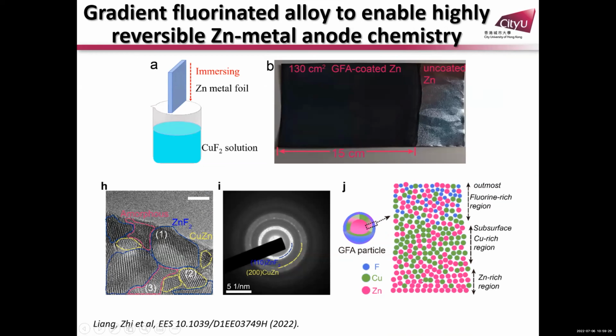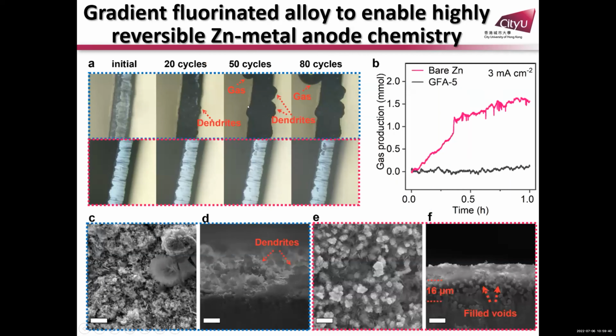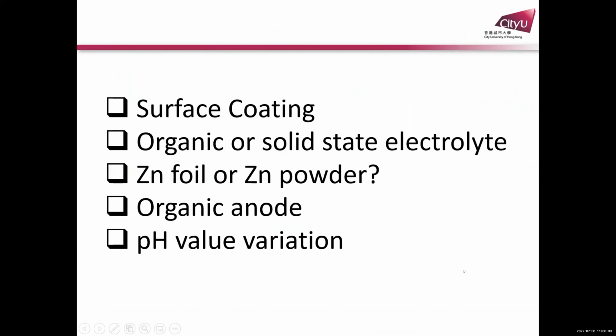So in this work, we develop a kind of gradient coating with zinc fluoride and alloy on the surface. With the zinc fluoride and alloy coating, we keep the good kinetics. And the hydrogen evolution, you see the gas come out, the pressure induced by the gas. But with our coating you don't have gas anymore, and more like a uniform structure of the surface. This is based on the coating strategy.